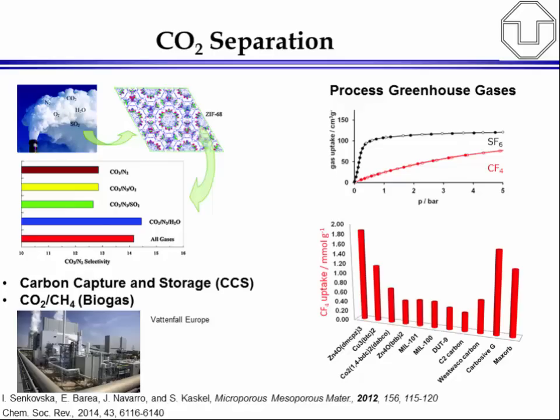This is not so challenging actually, to find a good separation material to separate CO2 from nitrogen in dry air, but it is more challenging if you have a presence of water or other trace gases like sulfur oxides, SO2, SO3, and so on. And this slide here, I've also cited the review on the bottom, is a newer review on separation applications, showing that nowadays also MOFs are available that have a good tolerance towards water because they are very hydrophobic, but still have a good selectivity for the capture of CO2.